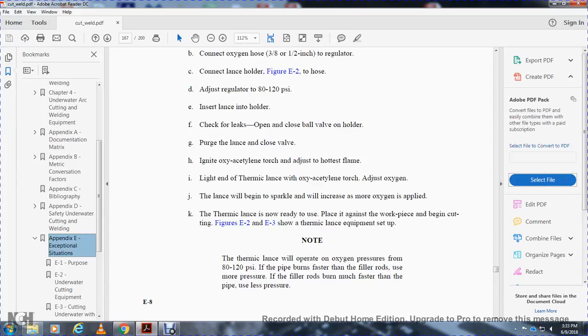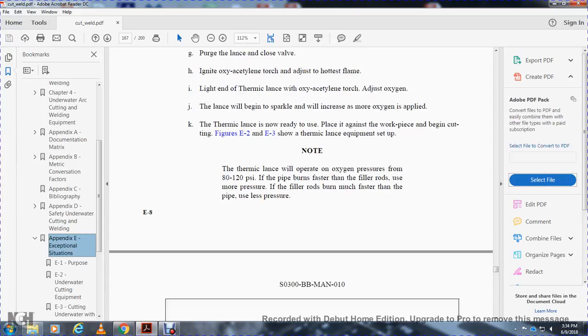The thermic lance will operate with oxygen pressure of 80 to 120 psi. If the pipe burns faster than the filler rods, use more pressure. If the filler rods burn much faster than the pipe, use less pressure.